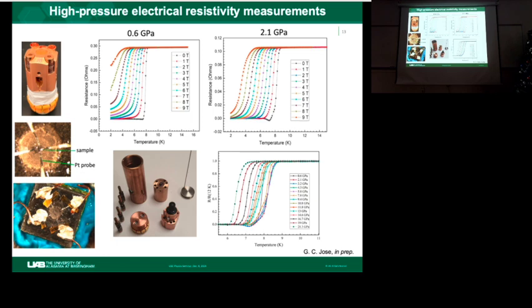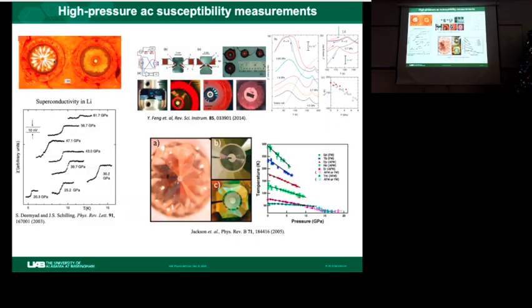And we can also use different types of diamond anvil cells. This type is just screw-driven, so you can simply tighten the screws and apply pressure. And this is another type that allows you to change the pressure in situ at any temperature and magnetic field. And this is an example showing resistance measurements on a superconductor under different pressures and different magnetic field conditions. So you can learn how the superconducting state changes with pressure and magnetic field.